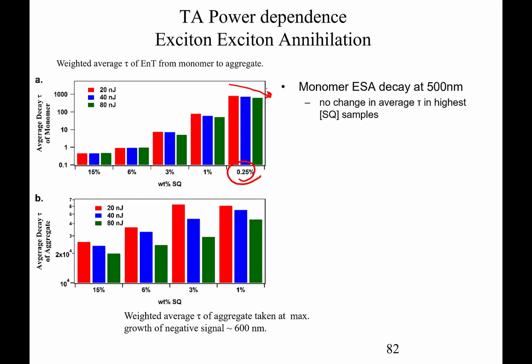So this is good evidence that when we have a low concentration of Squaraines in polymethyl methacrylate, and we're exciting the monomers, when we look at the excited state absorption at 500 nanometers, this is telling us that those excitons in the monomers are finding each other at low concentrations. What we also find, by the way, is that for our 15% samples, the decay rate is actually rather large. The decay time is low. That's because these excitons are actually transferring into the aggregates. But we also notice that the pump power dependence is very little. There's a flat, horizontal line here, and that demonstrates that there is relatively little exciton annihilation that we can observe in here. And that's of course because all those excited states have migrated over to the aggregates.